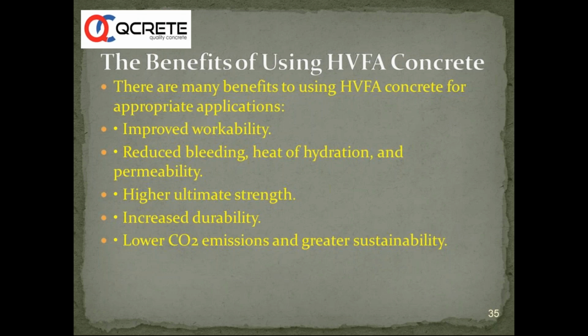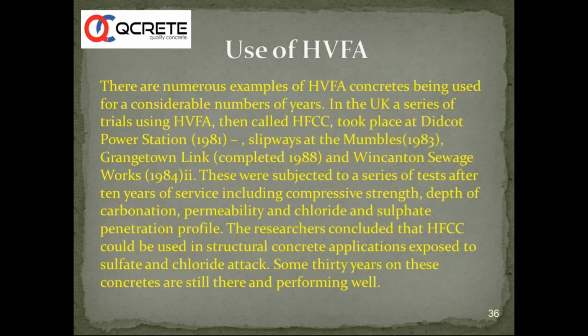A lot of structures have been built. There are numerous examples. It is not new, actually, as I've been talking about. In the UK, a series of trials using HVFA, then called HFCC, high amount of fly ash cement concrete, took place in Didcot Power Station, slipways of Mumbles, Grangetown Link, Wincanton Sewage Works, etc. These were subjected to series of tests after 10 years of service, including compressive strength, depth of carbonation, permeability, and chloride and sulfate penetration profile. The researchers concluded that HFCC could be used in structural concrete applications exposed to sulfate and chloride attacks.